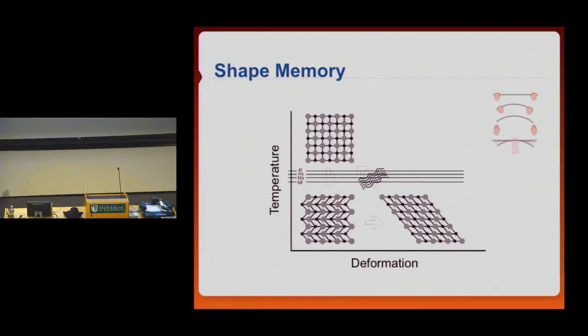We start with a cubic structure. It's actually a cesium chloride structure, a superlattice, ordered structure. And above these transformation temperatures, typically I'm only talking about the transformation temperature, although it's actually 4 different transformation temperatures, and it's a band of temperatures. But from a functional perspective, only one is important, and that is this uppermost.